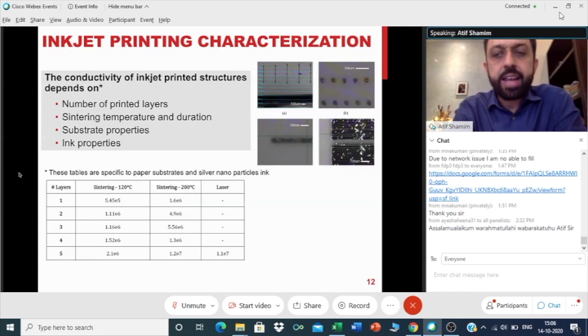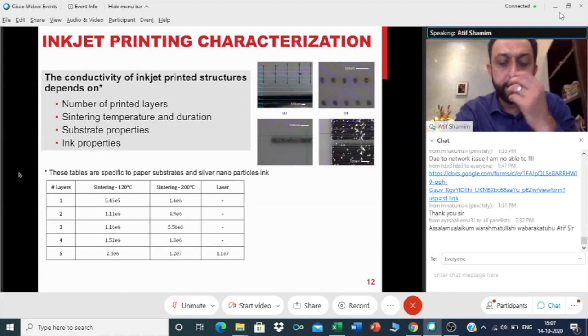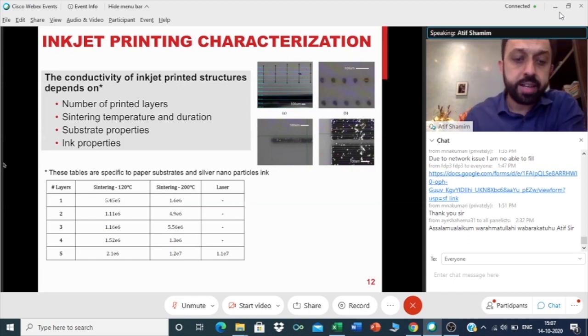conductivity starts to increase, and it makes sense because for every layer there's a limited number of nanoparticles. Particles are by percentage weight in that system. You print, you have some nanoparticles containing ink, but then you print another layer on top of it, more nanoparticles stuffed in, and so on. So basically, that's how you get the kind of conductivity. What was encouraging was, and this is, we just started with a commercial ink on a regular photo paper